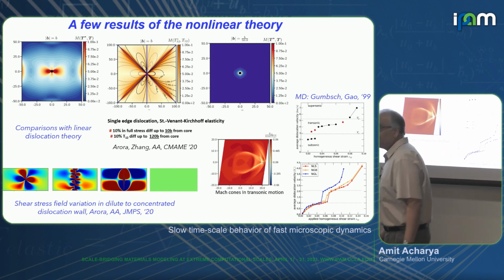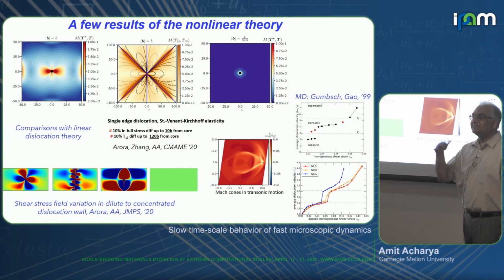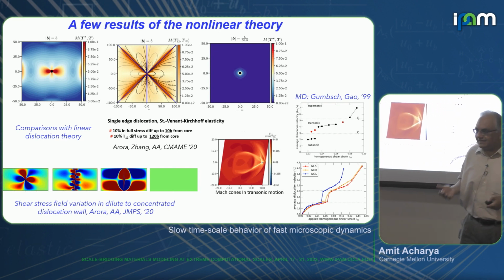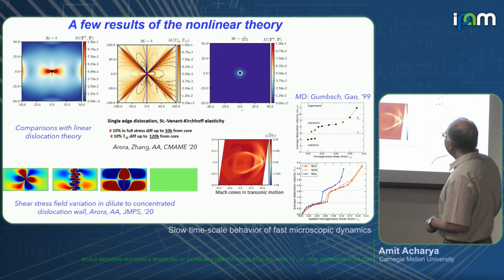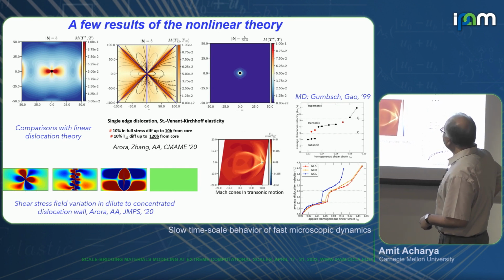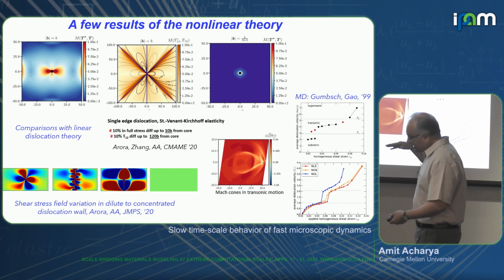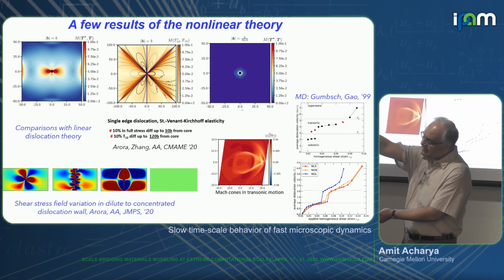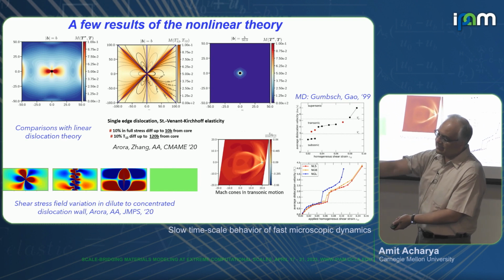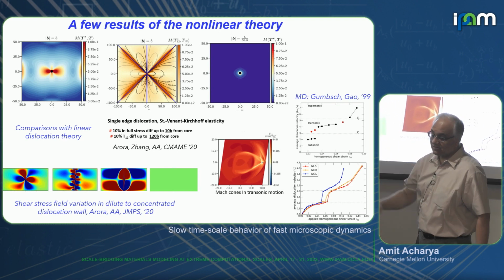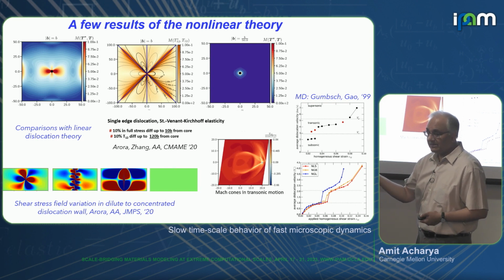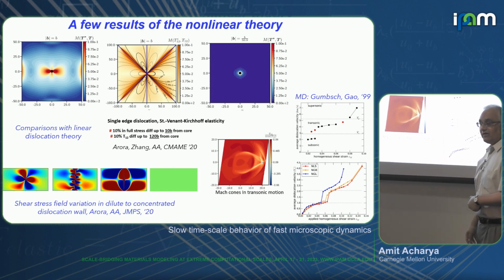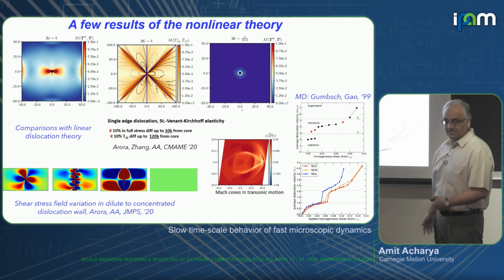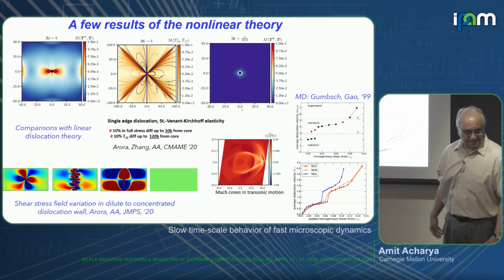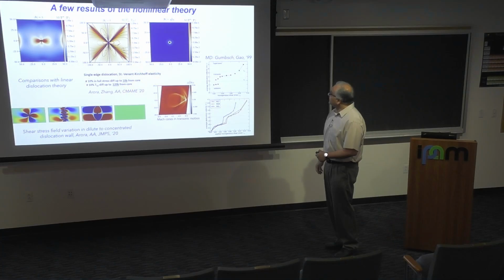So B over 50, which is expected, I mean, in the energy, okay? And then there are, these are like, if you are, this is a problem where you take a pre-stressed sheet and you launch a dislocation in the, and it moves, so depending upon the energy available because of pre-stressing, you can go faster than the shear wave speed, so then you're supposed to see Mach cones, you do. These are calculations. And actually, in MD, this is a science or a nature paper.